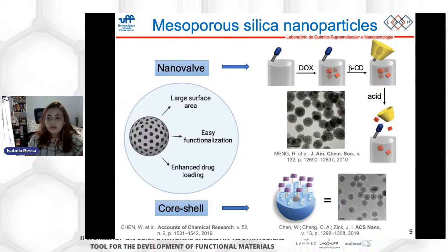This nanoparticle, as well as other inorganic nanoparticles, displays distinctive properties including corrosion resistance and high chemical, mechanical, and thermal stability. Moreover, mesoporous silica nanoparticles present modifiable characteristics like tunable pore diameter in the range of 2 to 15 nanometers, a large pore volume, and a high surface area.